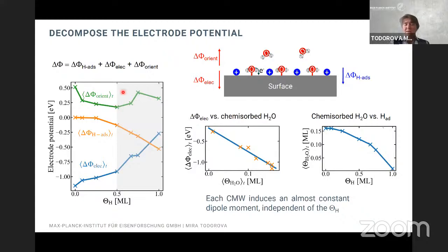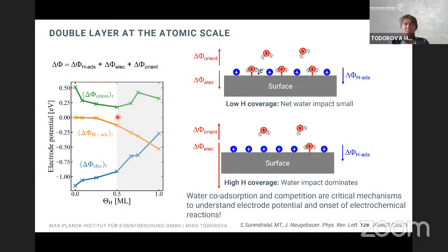they no longer cancel each other. So there is a contribution also from the water-induced changes in the electrode potential, which are, of course, then reflected in the output. So what we can say is that at low coverages, the net water impact is small, while at high coverages, the water impact dominates. So it seems that this competition between water co-adsorption and hydrogen co-adsorption is a critical mechanism to understand the electrode potential and the onset of the electrochemical reactions.